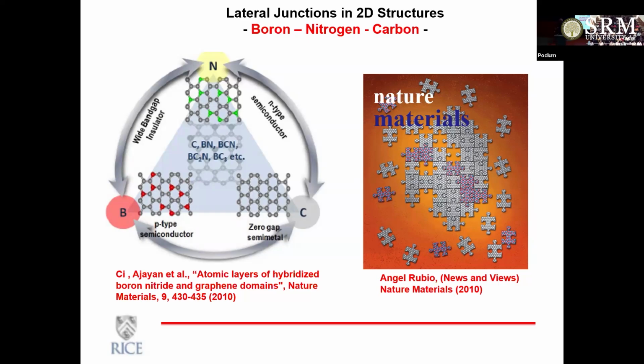So you can see this is exactly what we got. Instead of getting a uniform BCN phase, we got boron nitride domains and carbon domains. But because they are isostructural, because the lattice parameter is almost the same, they get nicely stitched together at the edges, right? So you have a single atom thin layer with nanoscale domains of boron nitride and carbon stitched together, almost dispersed throughout, depending on the composition that you use. So that was interesting. This is the first time anyone has seen that you can create a lateral heterostructure in a single atomically thin layer.